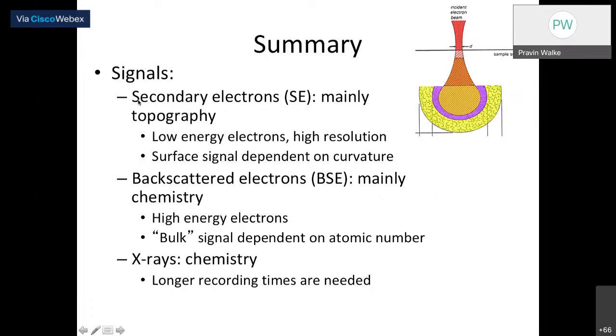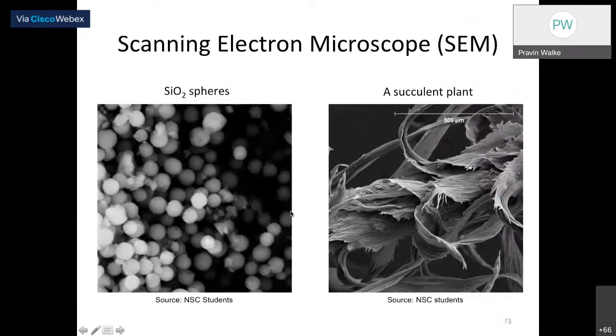As we know, these are the different signals and the information we can get from them. For example, from the secondary electrons, we mainly get the topography image. From the backscattered electrons, we mainly find out the chemistry. X-rays also give you important information about the chemistry, but they take a longer recording time and may damage the sample, so X-ray is a time-consuming process. These are the different points in the summary of the scanning electron microscope.